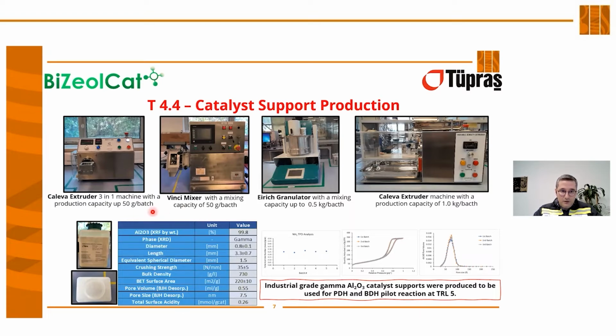In this table you can see some critical properties of our support. This is high purity gamma alumina with a very low diameter, and crushing strength is 45 Newton per millimeter, enough for the propane dehydrogenation reaction. The surface area is higher than 200 meters square per gram. So we can say that industrial grade gamma alumina support was produced to be used for PDH and BDH at the TRL 5 level.